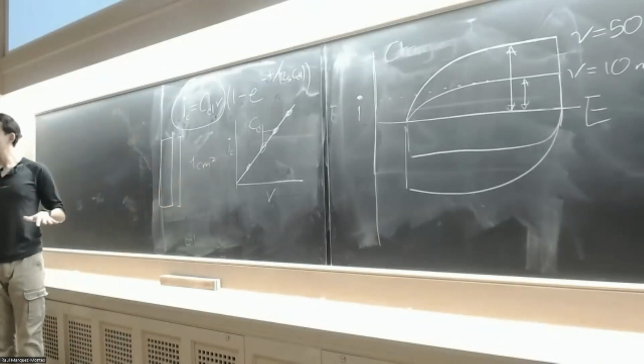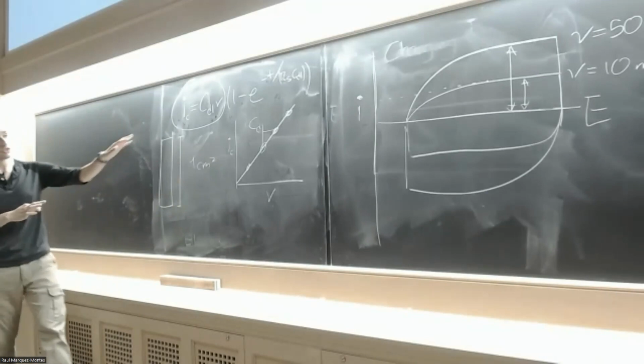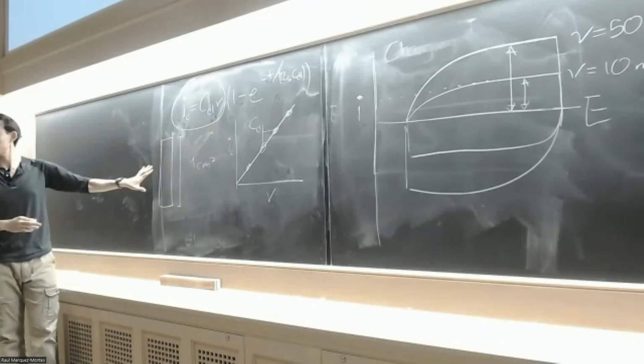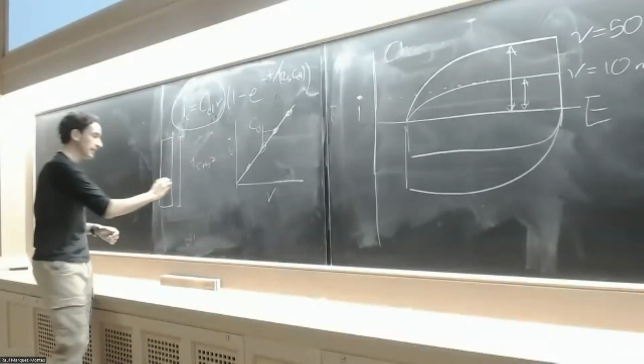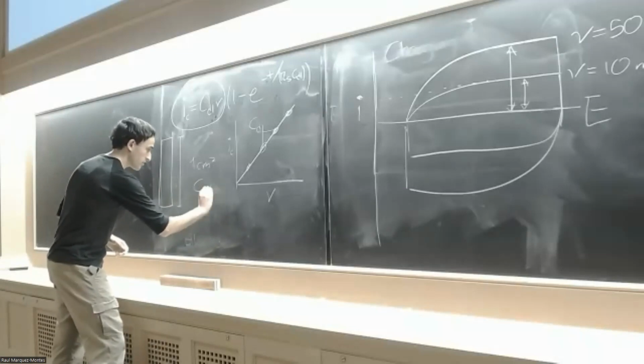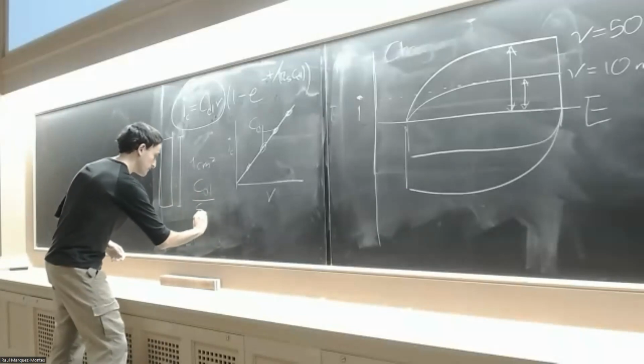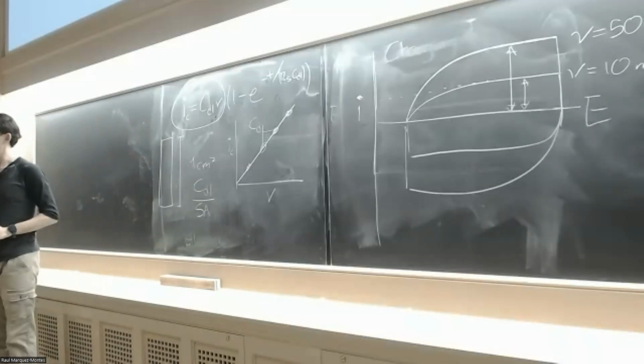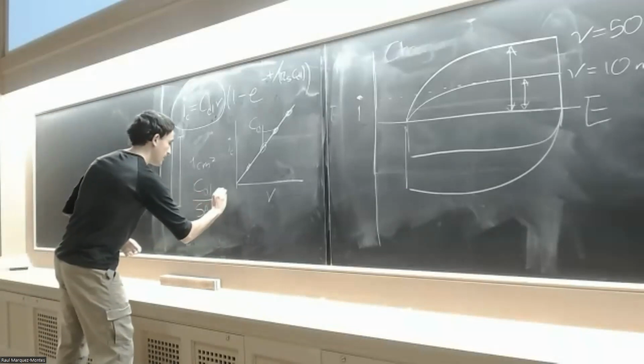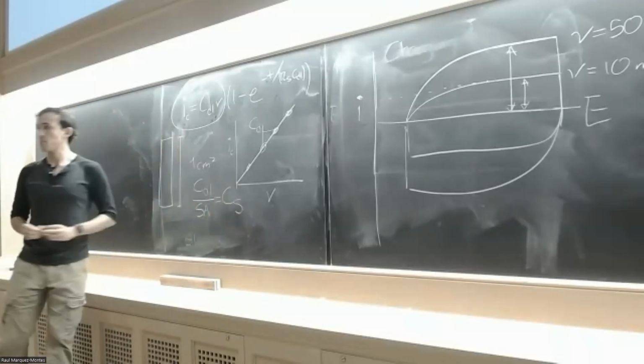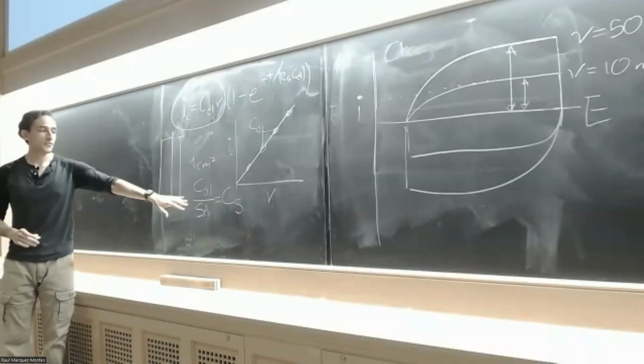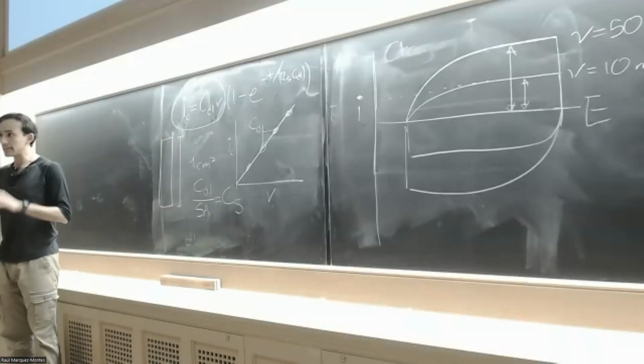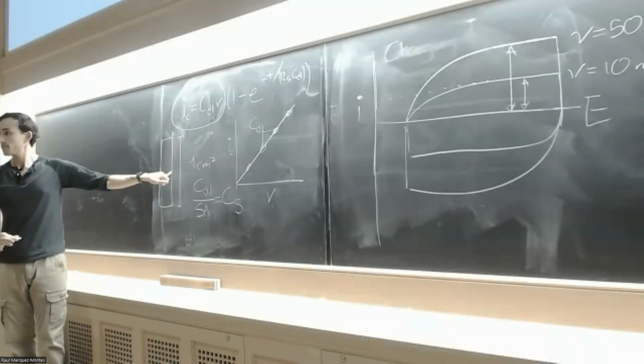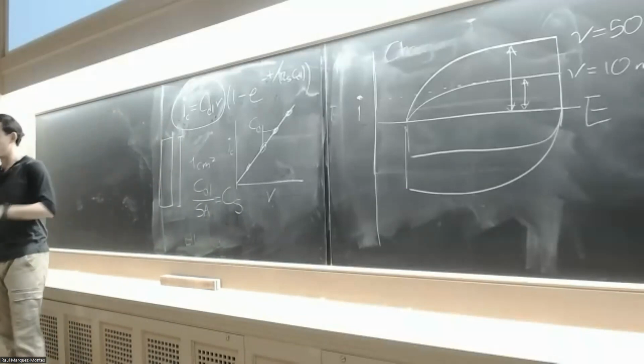If we know that, and then we measure the double layer capacitance of this material, now we can relate the double layer capacitance to the surface area. And this is known as the specific capacitance. So this specific capacitance is only applicable to this material, and this material as pure as we use it.